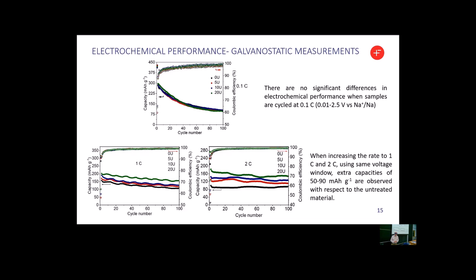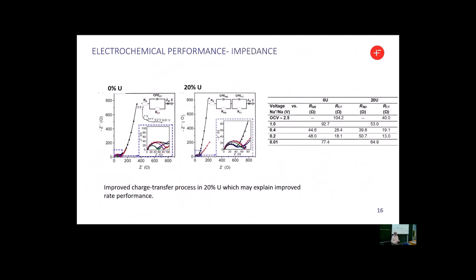The electrochemical performance doesn't change too much except in terms of stability under cycling. The more urea that's used in the synthesis, up to 20% by weight, the higher the capacity retention. So the reduction improves cyclability. If we look at the impedance, you can see that the charge transfer resistance decreases on reduction with urea. And that's what we believe improves the rate performance, the higher performance at higher rates.